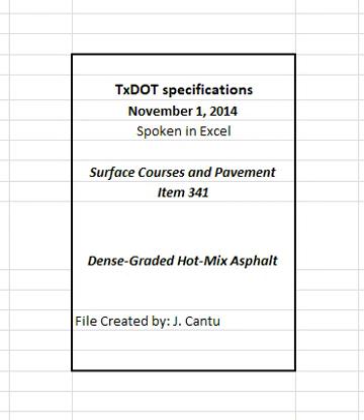4.4.2.1.13 Trial batch testing. Test the trial batch to ensure the mixture produced using the proposed JMF1 meets the mixture requirements in Table 11. Ensure the trial batch mixture is also in compliance with the Hamburg wheel requirement in Table 10. Use a department-approved laboratory to perform the Hamburg wheel test on the trial batch mixture or request that the department perform the Hamburg wheel test. The engineer will be allowed 10 working days to provide the contractor with Hamburg wheel test results on the trial batch. Provide the engineer with a copy of the trial batch test results.